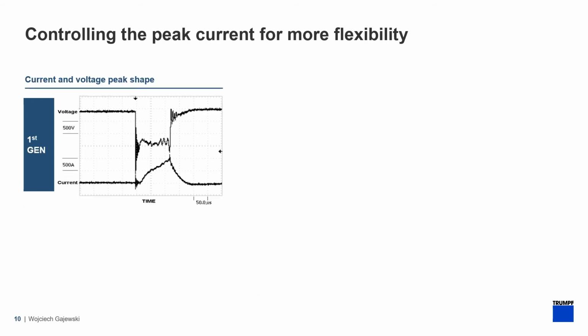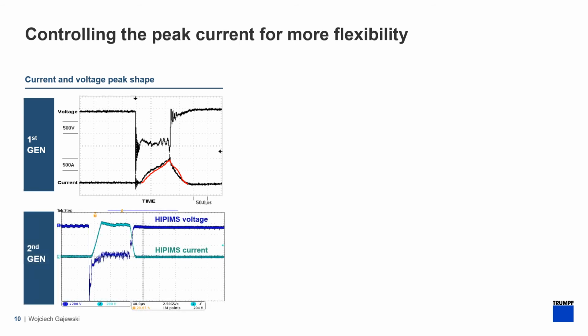A natural step in the development was therefore to change from the triangular shape of the HIPIMS current pulse to the rectangular one, in which we are able to maintain a constant current during the pulse. Such a change has been shown to have a dramatic influence on the plasma chemistry. Here we are presenting an OES signal recorded with a rectangular shape of the HIPIMS pulse in an argon-oxygen mixture of gases on the titanium target.